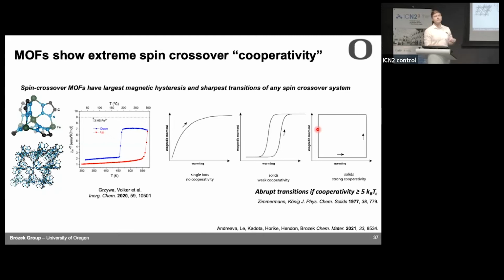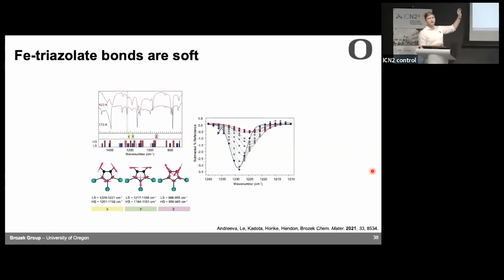What does cooperativity even mean? But they said if the energy of your cooperativity was 5 times your thermal energy, then you should see this. So that was this prediction, okay? So we wanted to study this. So we played the same trick. We measured the variable temperature IR of iron triazolate. Here's the triazolate stretch. It's really temperature dependent.